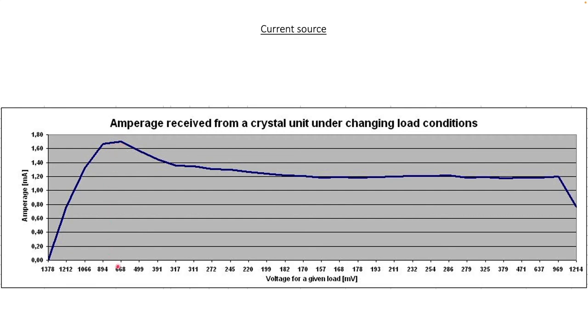When further reducing this load resistor, we came to smaller and smaller voltages on the outer electrodes of the crystal cell, so 668 millivolts, 499 millivolts. And when looking at the current that was registered, one can see that the crystal cell really works as a current source, which means that it can maintain a stable current output over a broad range of load resistors and a resulting broad range of voltages on its outer electrodes. Here in this case shown from 157 millivolts up to 1.2 volts.